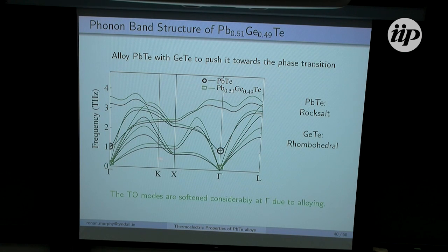And again, you can see away from the zone center, there are a few differences in the phonon dispersions, largely due to the different mass of the lead telluride and the alloy. But the main difference occurs right here at the gamma point, where you can see that the TO mode frequency, again as before, has dropped from about 1 terahertz down to about 0.1 terahertz in the alloy.